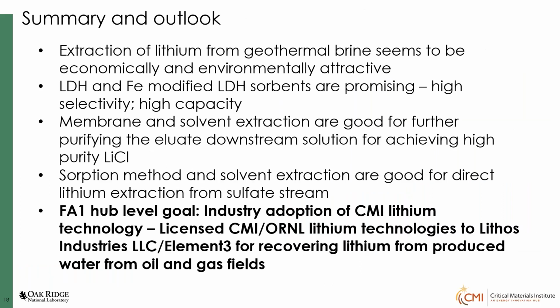To summarize my talk, mainly we showed that iron LDH and iron doped LDH sorbents are promising. They have high selectivity and high capacity, and we have developed membrane and solvent extraction for further purification, and sorption and solvent extraction for direct lithium from a sulfate stream. We have also done this from clay minerals, where we can use a sulfate stream. The challenge is that so far we have done mostly with simulated brines. So DOE is looking at whether we can do a real demonstration at a geothermal site. That will be coming up in the next year or two. Thank you.